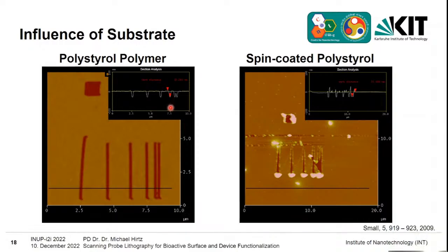And now you can also see here that you reveal a very nice pattern, and you can also have very fine details, which is not really done anymore here on the spin-coated polystyrene. And if you look at the close-up, you can also see that here you have fairly high, about 100 nanometer resolution at the end, where you can expose the substrate.